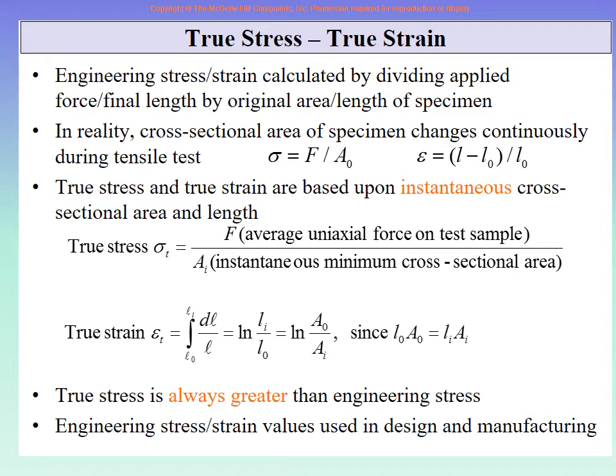Therefore, we do the engineering stress part. But if there is a machine where we have designed all that extra equipment of infrared or laser beam, and it keeps on hitting my sample as the area keeps changing, and it keeps on recording the current value of the diameter, then okay, we have no issue, right? That is the only thing, that it is very practically difficult and costly. And of course, in engineering, we want results which are good, accurate results, but economical. So that is the reason.